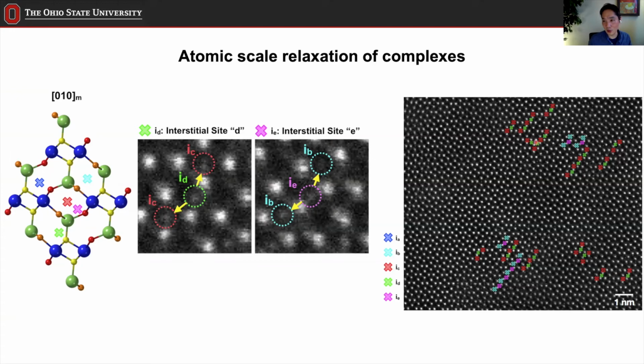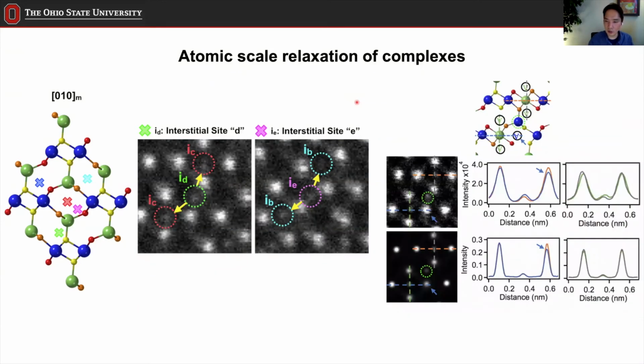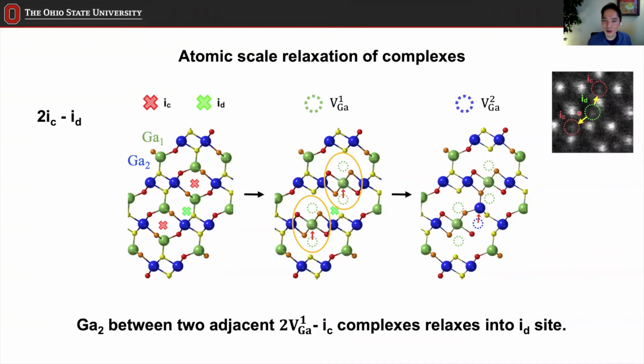And as you can see, they are always paired. So there's no occasion where ID appears without two ICs, and the same here, right? So IE always appears paired with IB intensities, right? We thought this was very interesting, but there was no model or defect formation mechanism that can explain this. But we were able to go deep in the quantitative analysis of all the intensities. I cannot go into all the details, but I can show you the finding, right? So all these models were constructed just based on the experiment. There's no energy minimization or any kind. There's no MD or DFT. This is purely an experimentally driven schematic of the model.